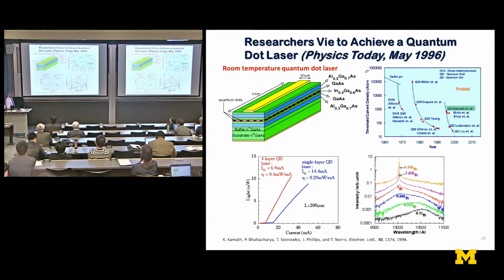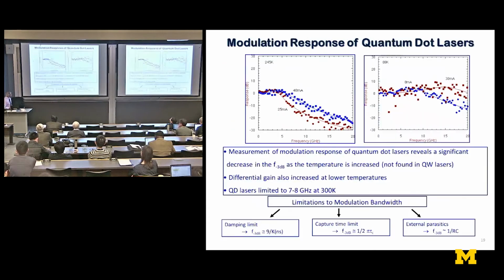But we sent it there because I knew there were probably other groups working, and I knew that this paper would be out in less than 5 weeks, 4 to 5 weeks. And indeed it was, and thank God we sent it there, because within a month there were 2 more papers with similar results. So that was that. So that was the first room temperature quantum dot laser, lasing at about 1 micron, as you can see.